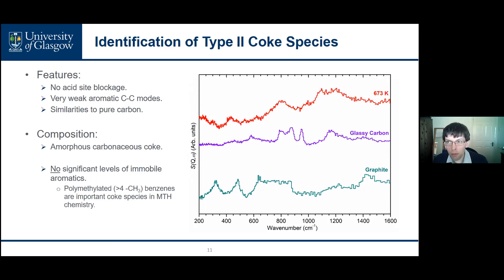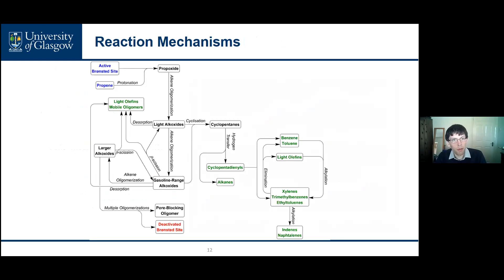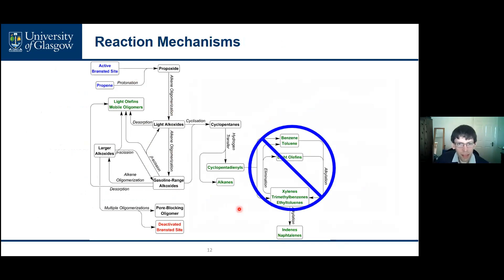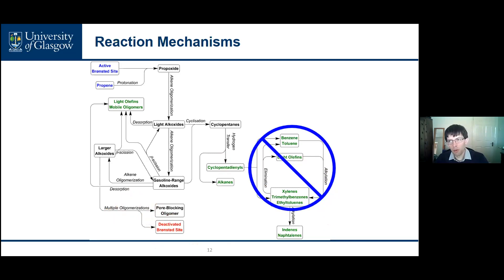Given these results, we can identify that the overall reaction mechanism for propene over ZSM-5 takes the form of a dual cycle hydrocarbon pool mechanism, quite similar to that observed for methanol over the same catalyst but with some important differences. At 473 Kelvin, there isn't enough energy for the cyclopentadienyl intermediates to undergo further conversion to produce aromatic species, so the aromatic cycle of this dual cycle is inactive. This leads to multiple oligomerizations and the formation of pore-blocking oligomers, causing the premature deactivation of the catalyst observed in the GC data.